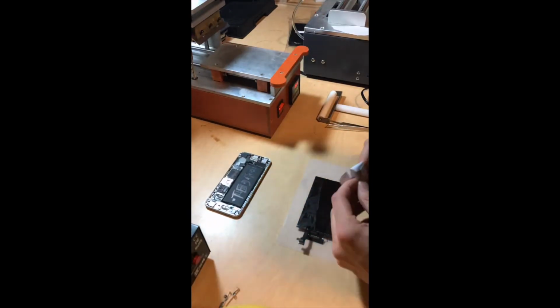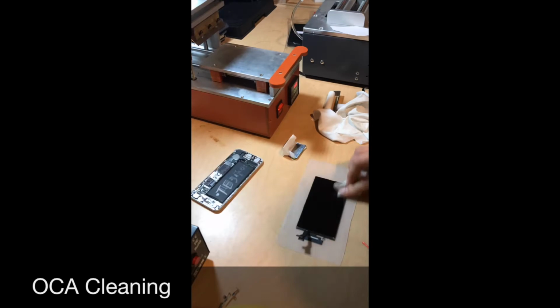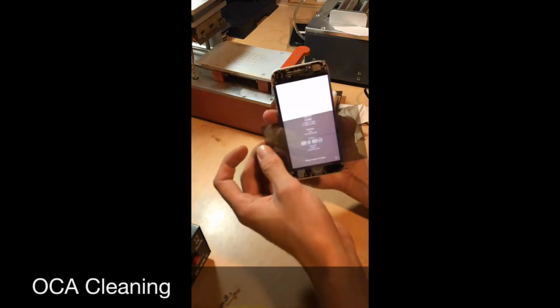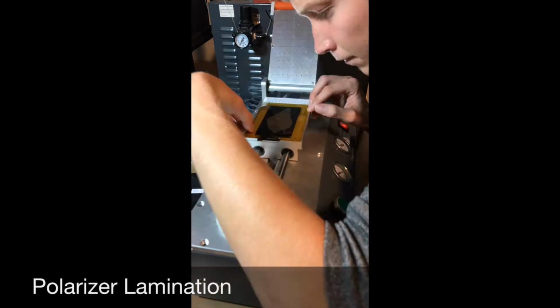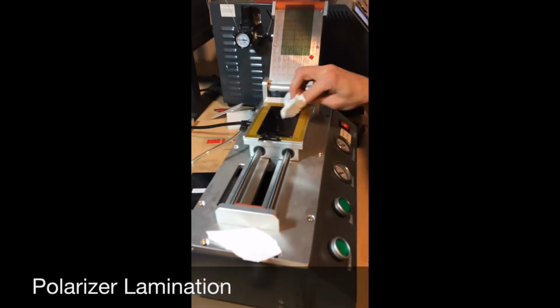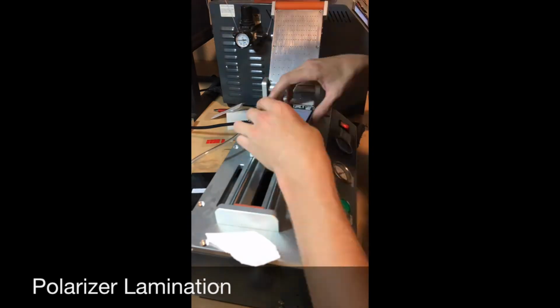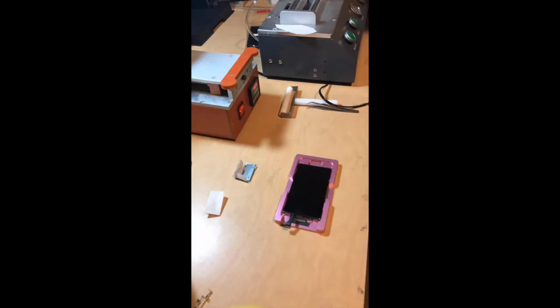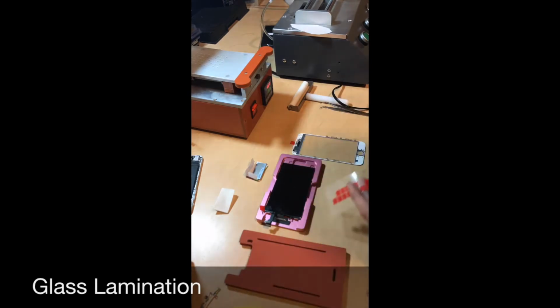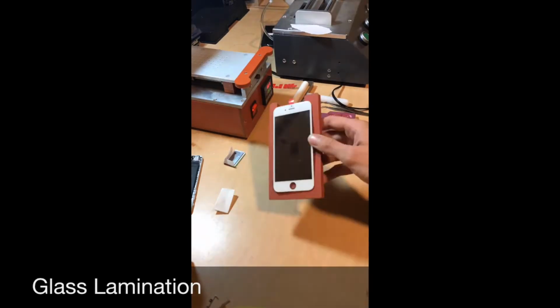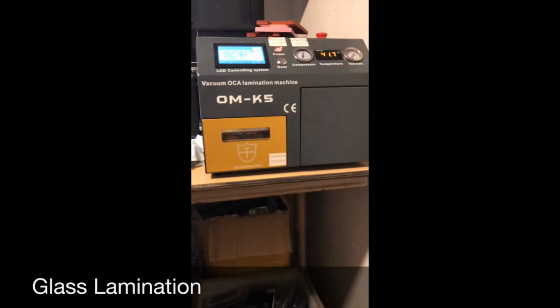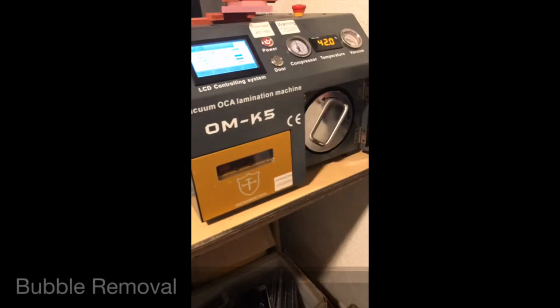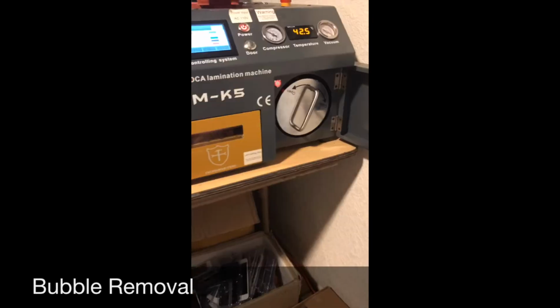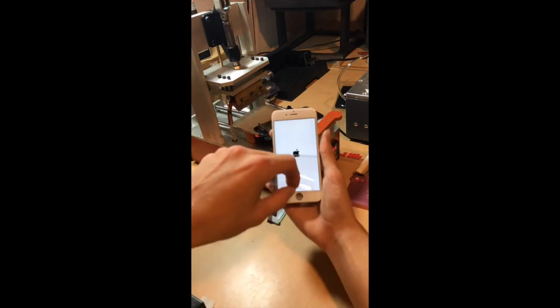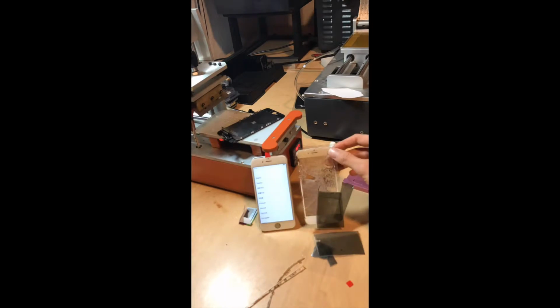Large amounts of OCA are removed by a razor blade, while smudges are removed with mass airflow sensor cleaner, which contains a high amount of N-hexane, which is a good solvent. The LCD is tested again before polarizer lamination. Two vacuum plates hold both the LCD and the polarizer steady, and then an automated process laminates the polarizer to the LCD. The glass can now be laminated onto the working LCD and digitizer. And then, once lamination is initiated, it is put into the vacuum OCA lamination machine. Bubbles are removed in the autoclave, and then the final product is tested, with the damaged glass and polarizer shown on the right.